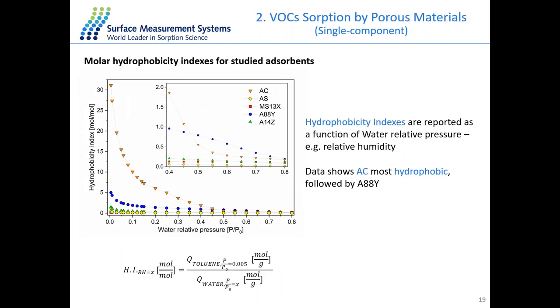And with the single component data, we can also calculate a parameter, the hydrophobicity index, with the equation here, just by simply dividing the amount of toluene uptake over the amount of water uptake. You will get a ratio between the two values, and you plot the values against the partial pressure, and then you will get a line like this one. Some information you can get from these lines: the more toluene that goes in relative to water, the more hydrophobic the material will be.